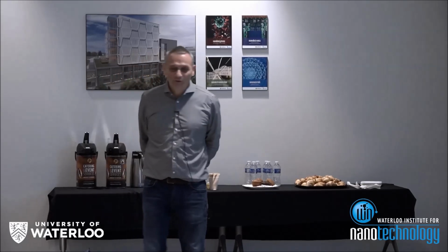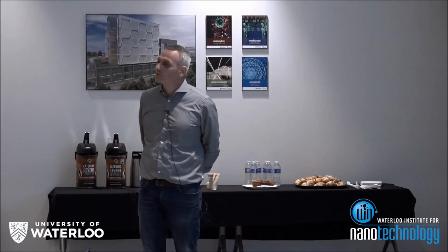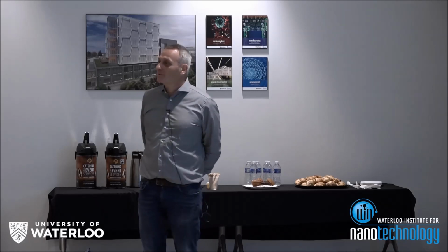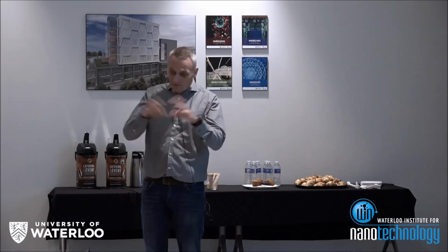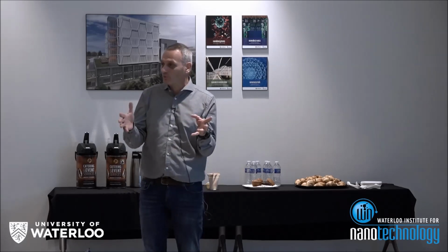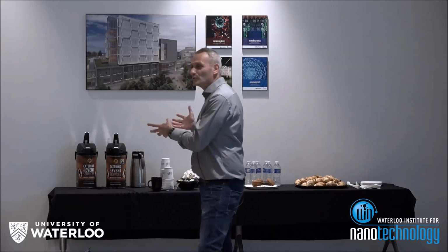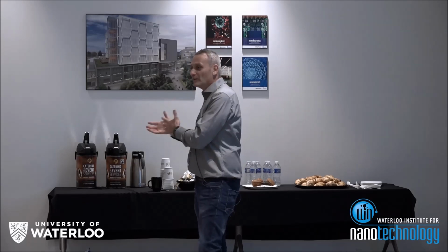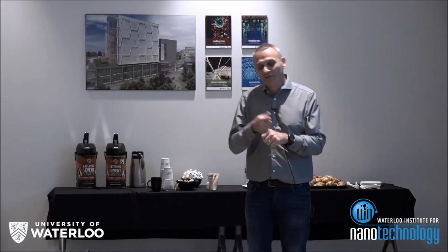Well, again, if we have a choice, we try to use low-cost technology. Silver nanowire transparent electrodes are compatible with roll-to-roll, but then afterwards, if you have to anneal in vacuum, somewhere you have to cut them and put them in a vacuum, so you can't do that with roll-to-roll. That's the first reason, an economical reason, not a scientific reason.